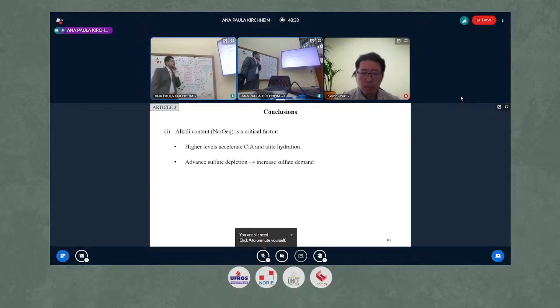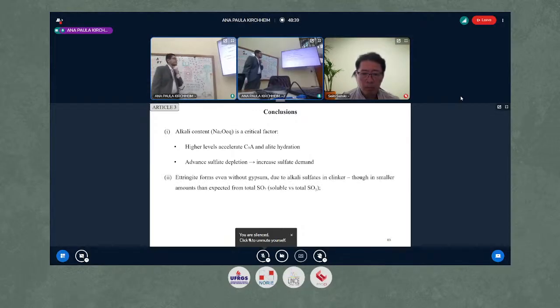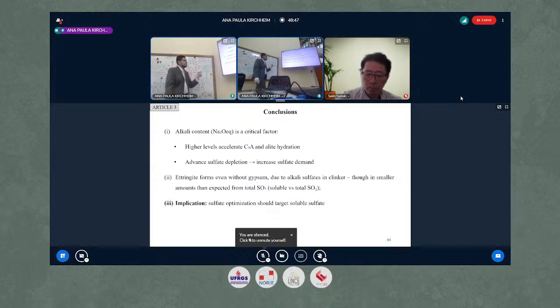Alkali is a critical factor because it increases C3A in early hydration, so increases sulfate demand. Ettringite forms even without gypsum, showing that indeed some part of the sulfate in clinker participates in the reaction. And so the indication is that the sulfate optimization should target soluble sulfate instead of total sulfate.